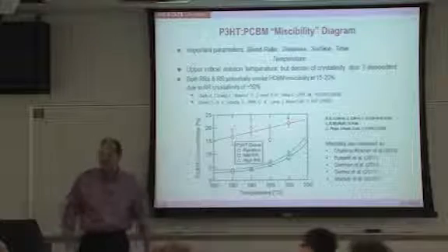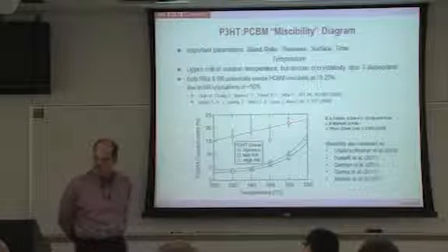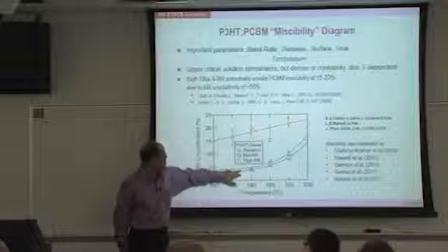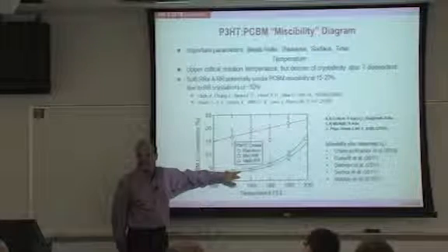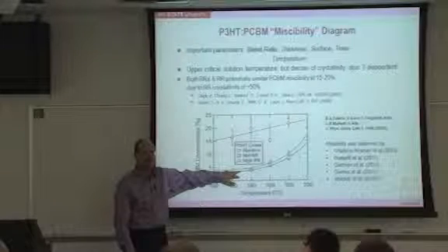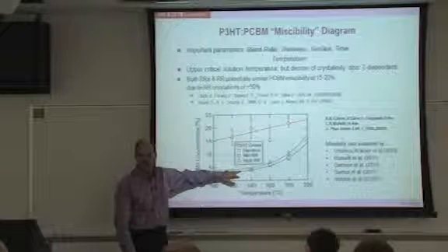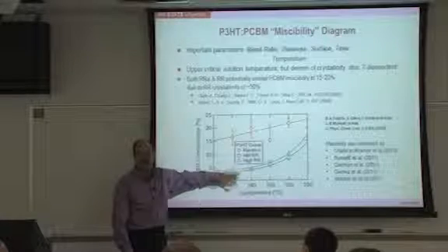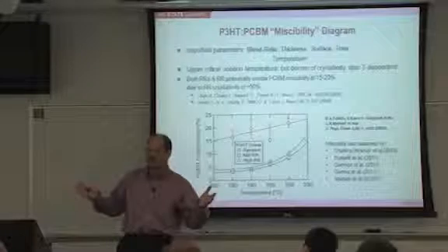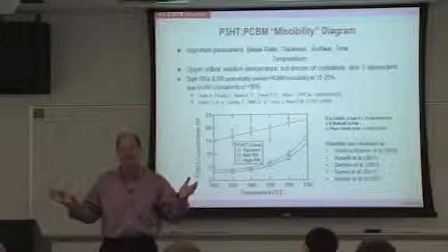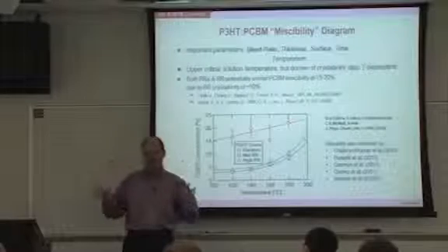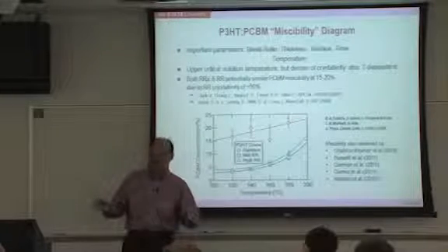Yes? I mean, here, these are for amorphous material or crystalline material? These are crystalline, so these are crystalline. Okay? So even in the crystalline P3HT phase, we know from WAXS there is no PCBM. But it's a semi-crystalline polymer. There is a fraction of no more than 30–50% of the P3HT, even in a homopolymer film, is in a crystalline phase.